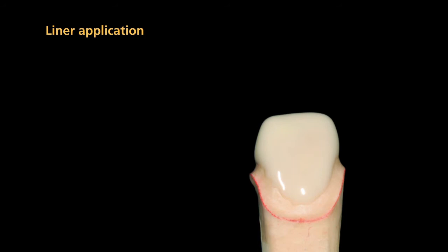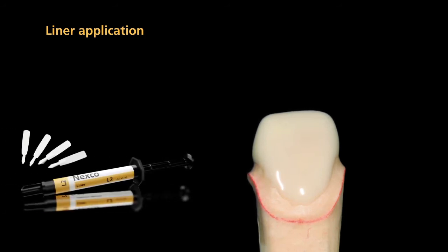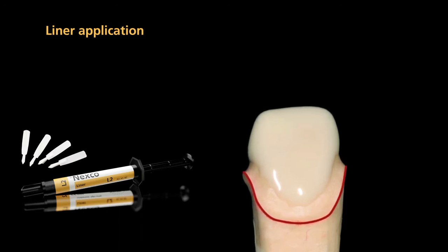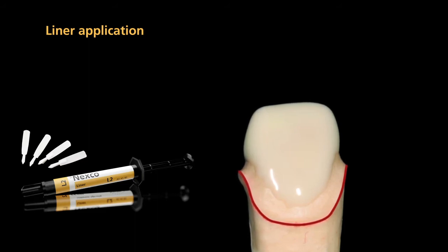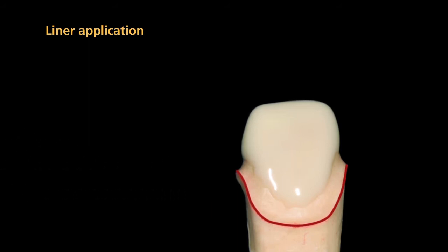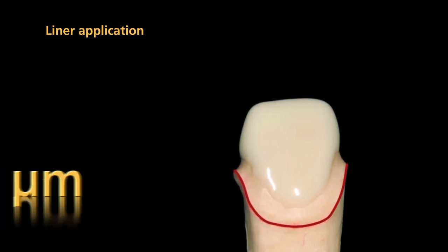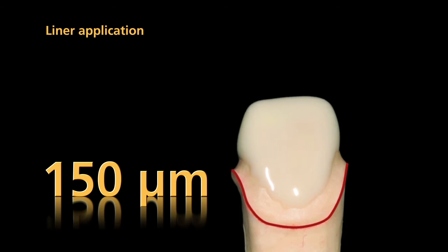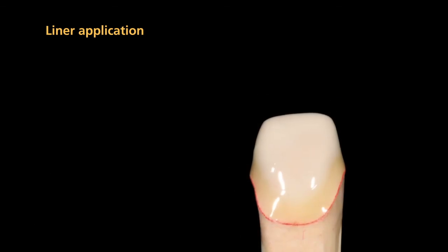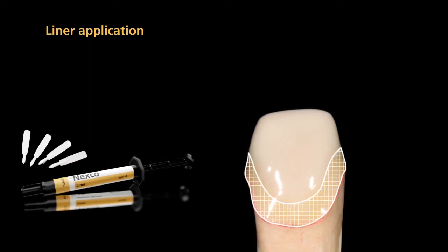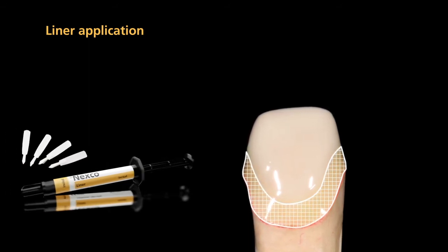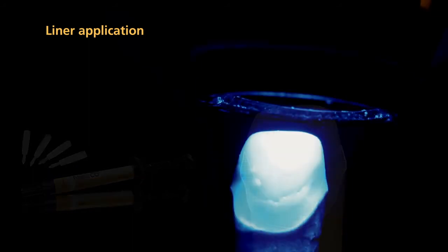Apply the liner thinly on the entire die surface and thin it out towards the preparation margin. It is important to fully cover all areas because the liner provides an essential bonding surface to the luting composite. Please note that the thickness of the liner coating should be at least 150 microns. To enhance the transmission of light in the cervical region, apply liner incisal to the marginal area. This measure provides a harmonious transition between the gingiva and the restoration.